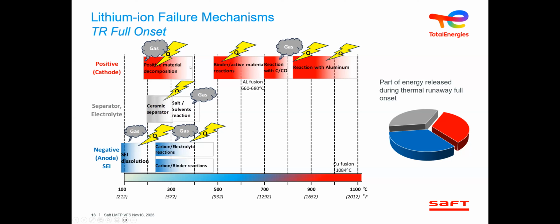And once this is happening, now you have heat, oxygen, and fuel from your electrolyte, which enter this cycle of thermal runaway. The more charged you are, the more energy you have to compound these reactions. But as soon as you have degradation of your substrate, which can lead to the aluminum, the anode degradation, and or your copper, you obtain metal fusion temperatures, which are extremely damaging and extremely hard to stop.